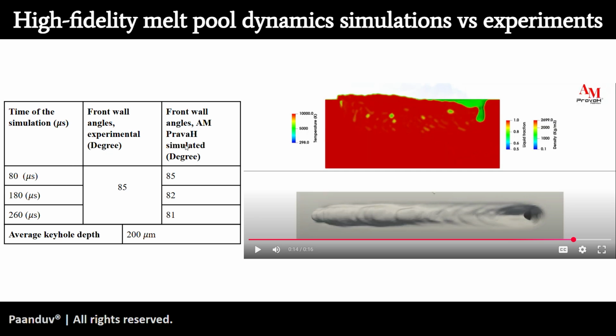Now let's look at some of the experimental comparisons. So we are looking at the front wall of the weld of the melt pool in this case, which is quite important in understanding the defects and how well the overall surface finish of your build part would be. So the front wall experimental angles were reported to be 85 degrees. See, 5 degrees short of 90 degrees.